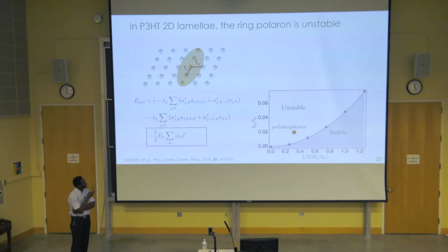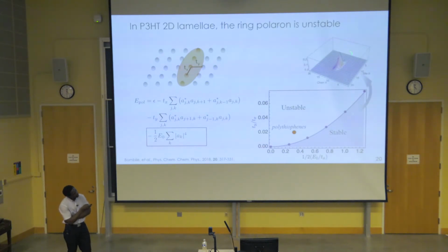And to rationalize that, we looked at how the binding energy for such a configuration will depend on the parameters that set its size. And what we found is that we have two regions, a stable region and an unstable region, depending on the parameters. And polythiophene happens to fall indeed in a region where the polaron is unstable. This is what a stable polaron will look like in this system. So I was warned about this alarm, so I will keep going.